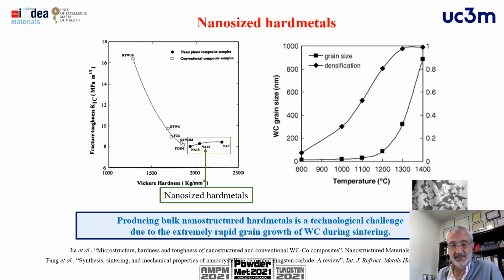The problem is that the tungsten carbide grain size increases strongly with the temperature. So we have to produce these nanostructured hard metals, which is a technological challenge, because the rapid growth of the tungsten carbide with the temperature avoids maintaining the hard metals in this group of the so-called nanosize hard metals. For this reason, it could be interesting to go to sintering techniques that avoid the grain growth during the sintering.